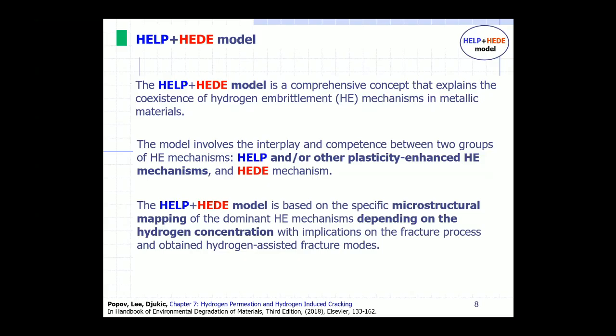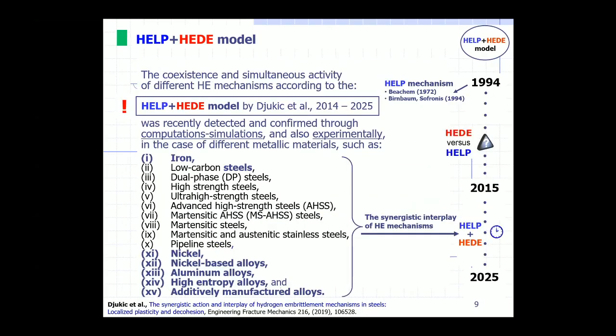Once again, HELP and other plasticity enhanced hydrogen embrittlement mechanisms. On the other side, the HEDE mechanism. And as I mentioned, hydrogen concentration is probably the most important factor, but also the most problematic factor, because nobody knows what the critical hydrogen concentration is, because we can measure hydrogen concentration, as we heard in a presentation by Professor, on various scales. So we have at nano and atomic scale, on lower scale hydrogen concentration, we have microscopic average hydrogen concentration, which we can measure. We still cannot measure the hydrogen concentration in the grain boundary or at this location. Nobody knows what the hydrogen concentration is at local level. So that's the problem with this concept.